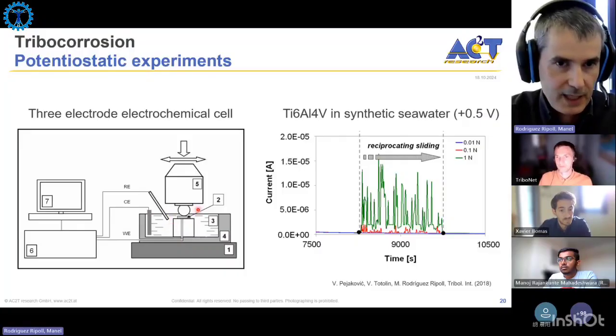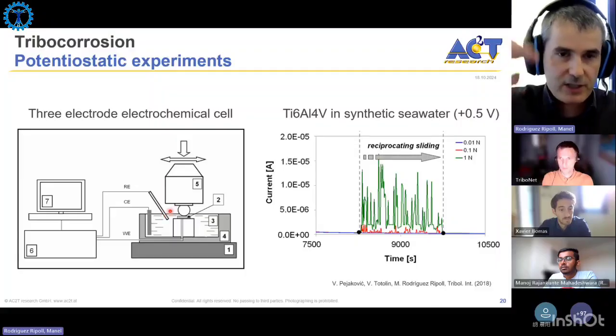And if we apply a potential, we saw before that in the passive domain the current is very low, in contrast to active materials, where we saw this anodic branch, where the current was increasing exponentially in this semi-logarithmic plot with increasing voltage. So here